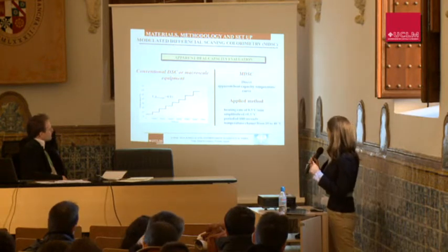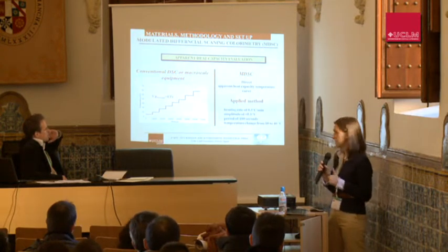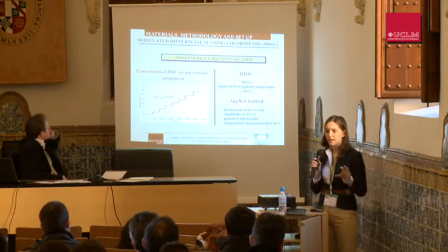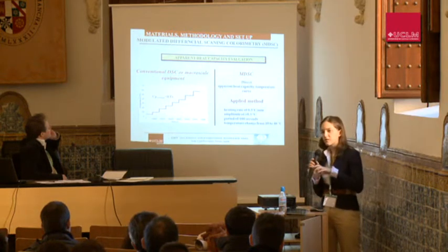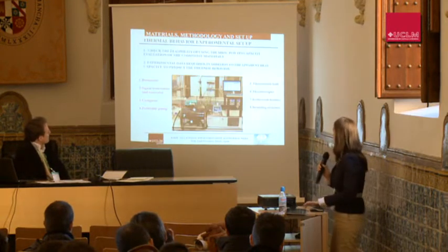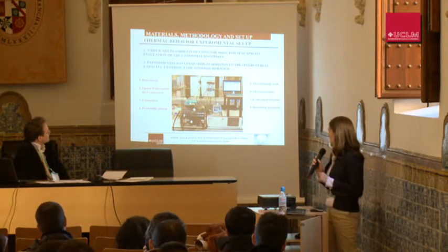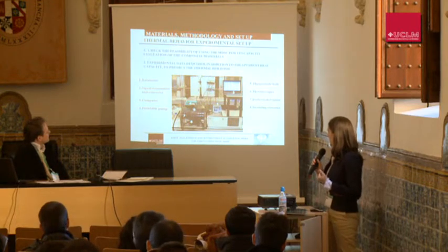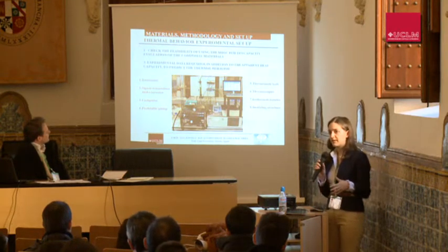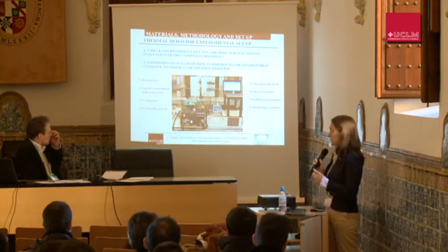We found that for this kind of materials the good conditions are: a heating rate of 0.5°C per minute, an amplitude of 0.5°C, a period of 100 seconds, and a temperature range from 10 to 40°C — since our melting point is 28°C, it is perfectly within this range. In order to check the feasibility of using modulated DSC for heat capacity evaluation and to obtain experimental data required for the prediction of thermal behaviour of PCM-containing materials, we designed and built the installation shown in the slide.